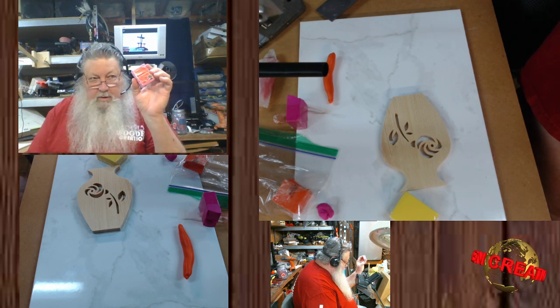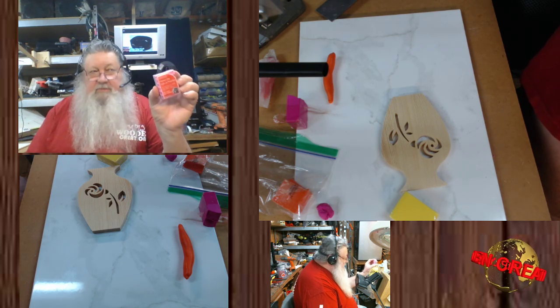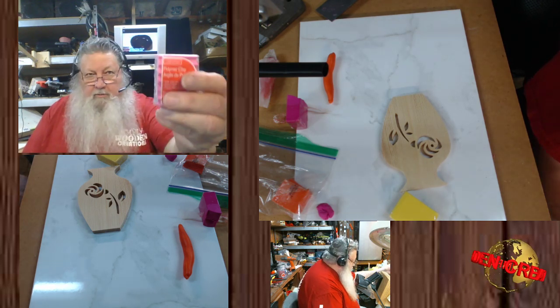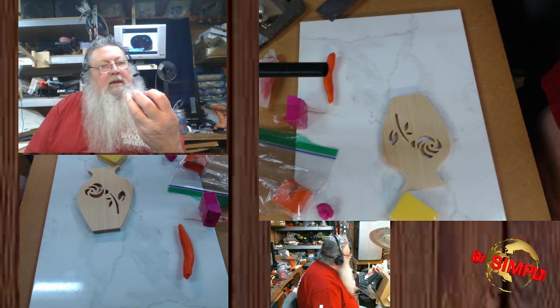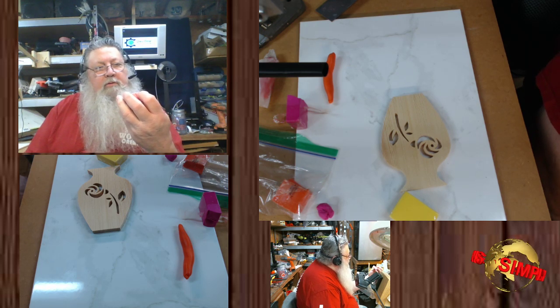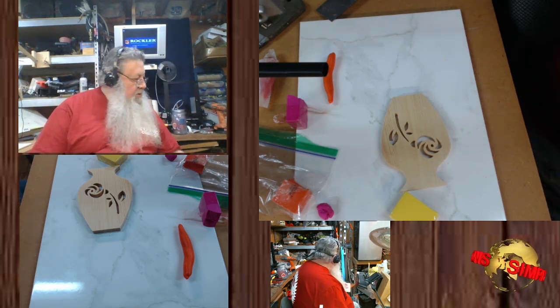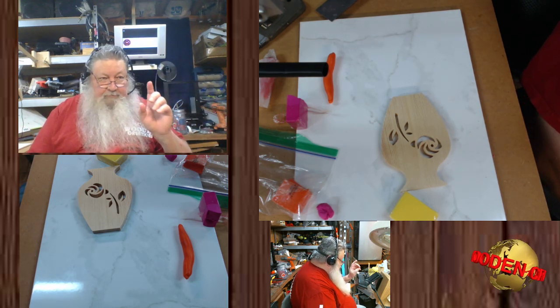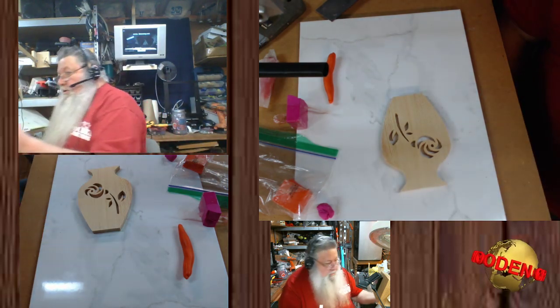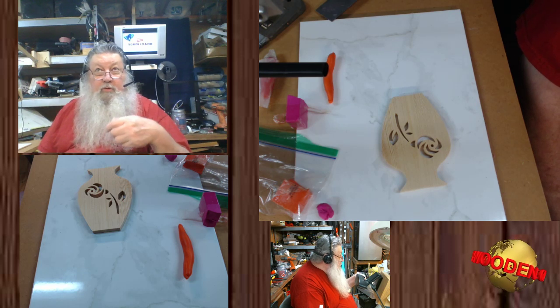Okay. So like I said, I know they got this at Michaels. This was their brand, and this was actually the cheapest I could find at the time. This is Craft Smart from Michaels, and it actually says on it, knead clay for 2 minutes, bake at 275 degrees for 15 minutes per quarter of an inch. That's the norm that I have read, 275 degrees for 15 minutes. But once again, you need to follow whatever brand you buy, their instructions. This particular brand that I bought from Hobby Lobby said 300 degrees for 0 to 30 minutes.